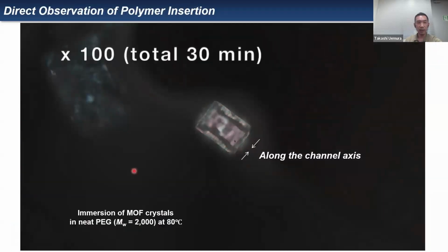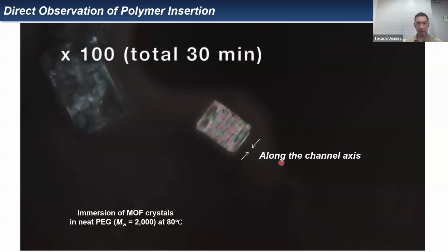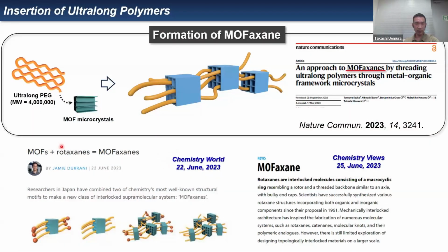Then, we can actually directly observe the polymer insertion phenomenon. That happened after the immersion of the MOF crystals into neat PEG like this, and it happened only along the channel axis. We could even insert ultra-long polymers with a molecular weight of several millions, allowing for the formation of MOFaxane by the threading of the ultra-long polymer chains through the metal organic framework microcrystals. We are really happy that this work was featured by many media in the world.